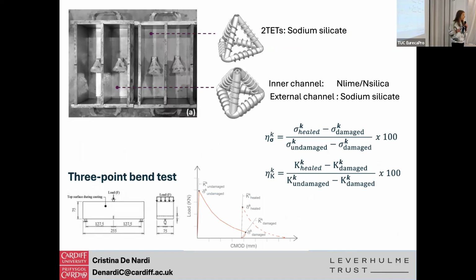We place them in the middle third of a concrete prisms. We use sodium silicate as a single component, or the sodium silicate in combination with nanolime or nanosilica, because those second parts can act as a promoter of the healing reactions. We test them under flexural test, and we analyze what we call index of healing in terms of strength and stiffness, which is not so complicated. We are just basically comparing the flexural strength after the healing in relation to the original strength before the damage, in relation to the residual flexural strength, which is this one.